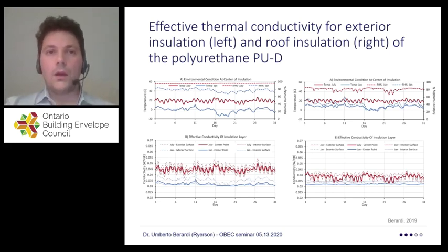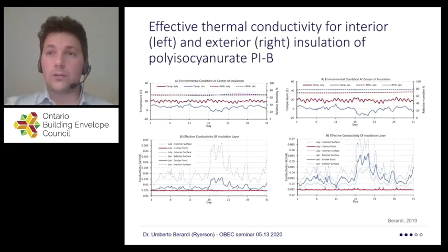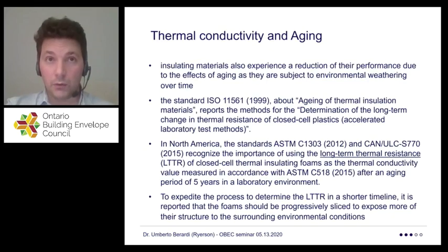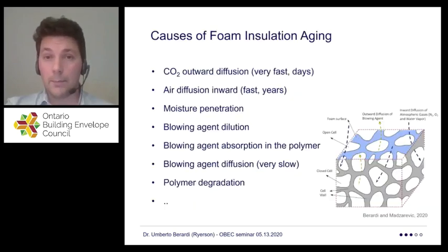And as soon as we went actually into July, we ended up having a lot of times values around 0.035. Same story with polyisocyanurate, but the reality is that with this product, the oscillation becomes quite bigger, quite more significant, quite more important to take into consideration. So you need to pay attention to these things because often we tend to underestimate and we do not consider that much the aging of these products. And the fact that materials tend to have an aging that, especially in foams, can be quite significant, but it's also happening in fiberglass and in mineral wool. And in a second, I'm going to show you what that means.